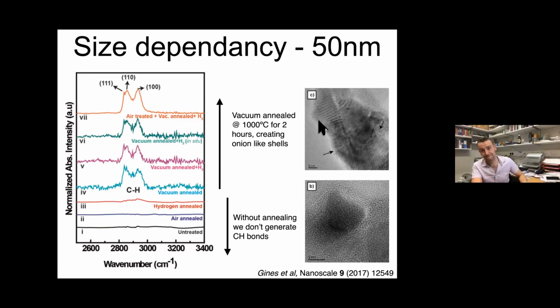And it works. So what you're seeing here is 50 nanometer particles. If you try and heat these in hydrogen gas, nothing happens, or very little. Certainly if you do it at 100 nanometers, nothing happens. But if you then anneal them in vacuum at 1000 degrees C or so for a few hours, there's an error bar on this temperature because we're never really sure about the furnace temperature.